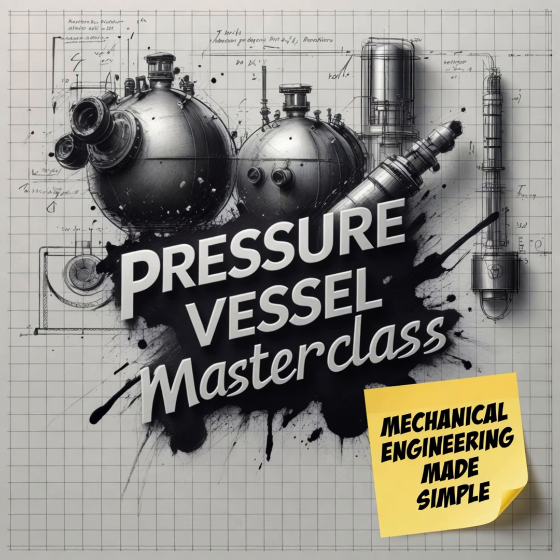Right, it permanently deforms. But the high-pressure gas inside doesn't care that the steel is yielding. The external force remains constant, so the steel stretches. The wall becomes thinner, which means there is less metal to hold the pressure, which causes the stress to increase further. Wow. So it's a runaway physical feedback loop that results in rapid catastrophic rupture. It just blows up. The force won't redistribute to a stronger part of the vessel. It just keeps pushing until it pops.